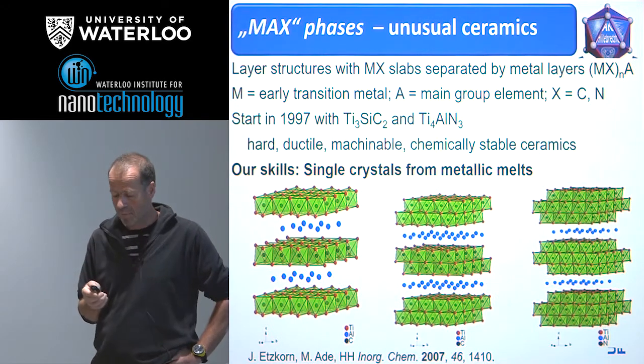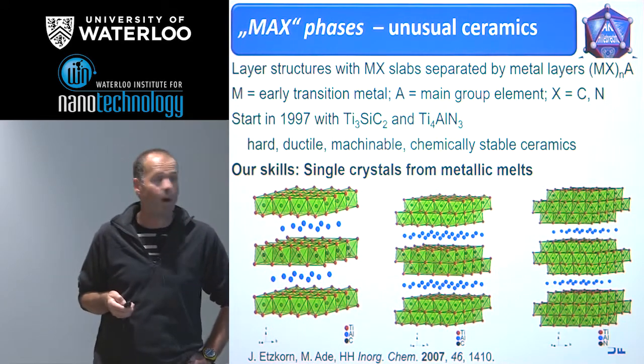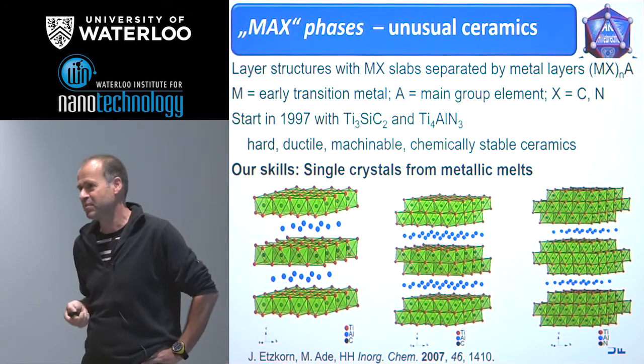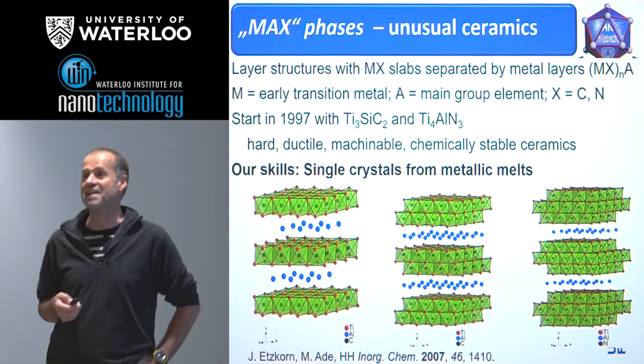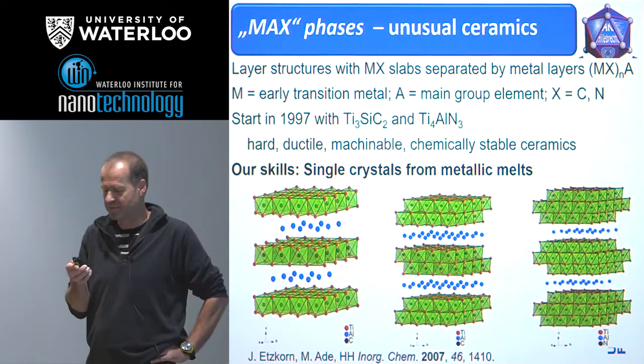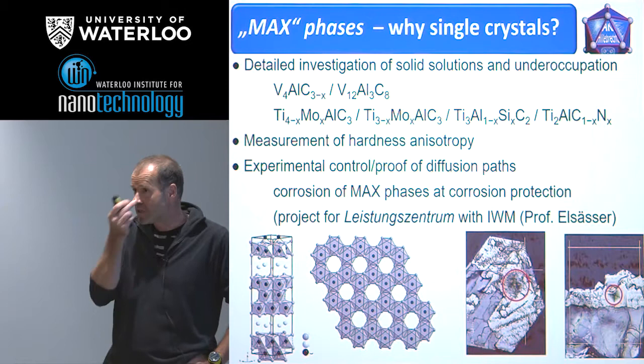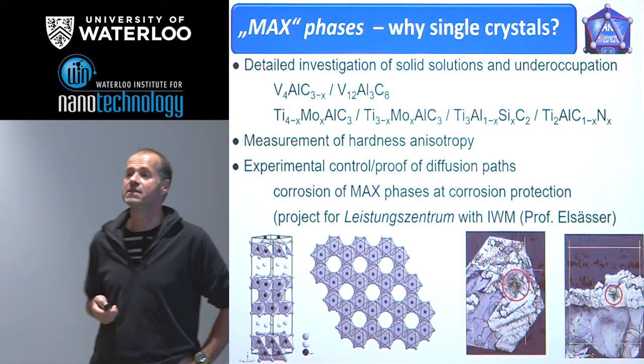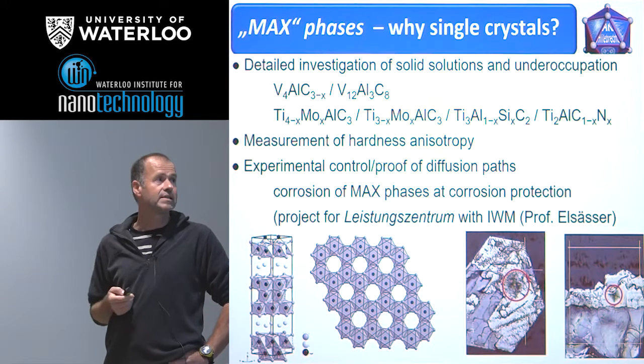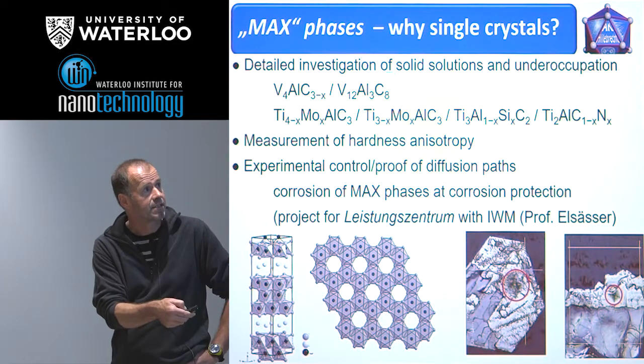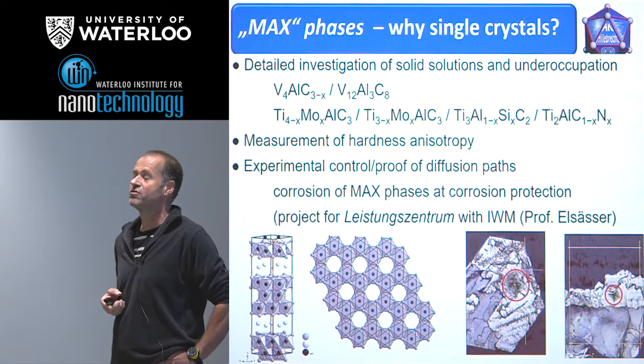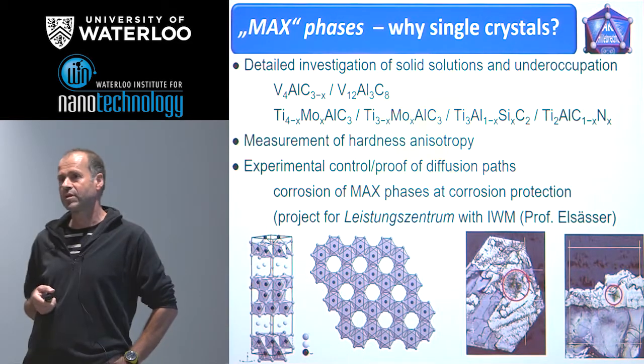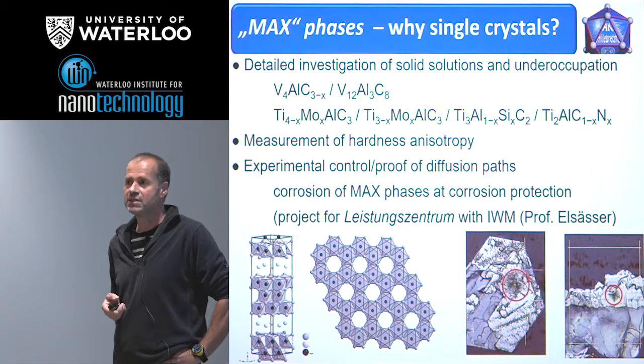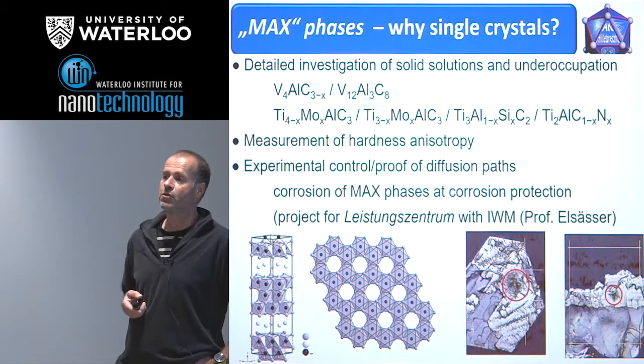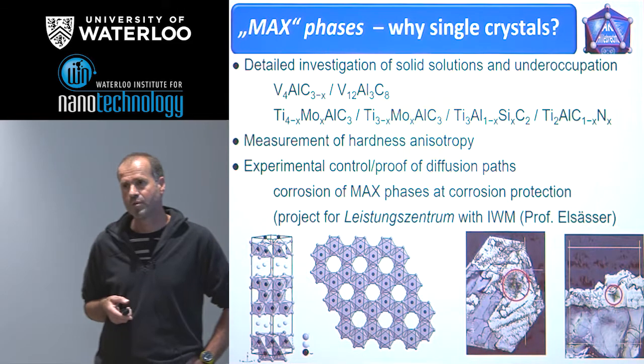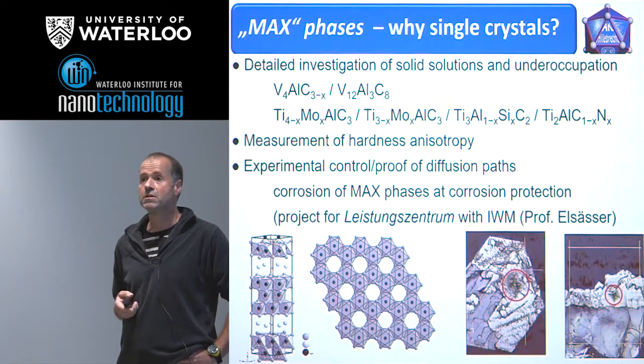But my question is, why single crystals? One answer is because we can. But that's not the only explanation. The other is that some of the investigations can or should be done based on single crystal data. One example are vacancies in the carbon positions. It is very well known that binary transition metal carbides are intrinsically non-stoichiometric. And we know that mechanical and especially physical properties depend on the non-stoichiometry.